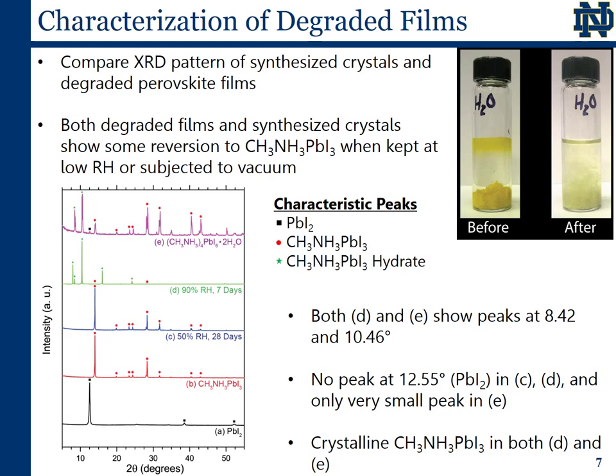Moreover, we do not see a peak arising at 12.5 degrees, which is characteristic of crystalline lead iodide. This provides evidence for the similarity between the two hydrate species. Additionally, we see the degraded perovskite films and the synthesized hydrate crystals both can show a reversion to crystalline methylammonium lead iodide when they're removed from a humid environment.